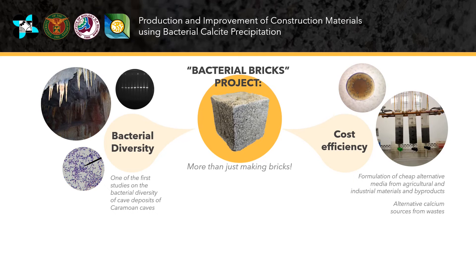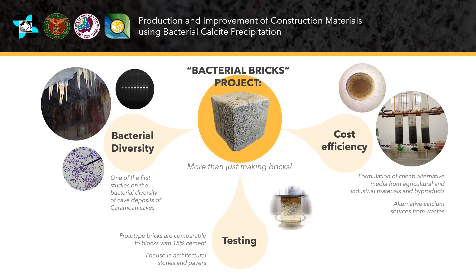We have already produced prototype bacterial bricks with strength comparable to sand blocks containing 15 percent cement. Our aim is to produce bricks that will be initially applied as architectural stones and pavers comparable to conventional counterparts. We will test our prototype bricks for compressive strength, fire and salt resistance, and water absorption, hopefully passing industry standards so that they can be used as alternatives to conventional bricks.